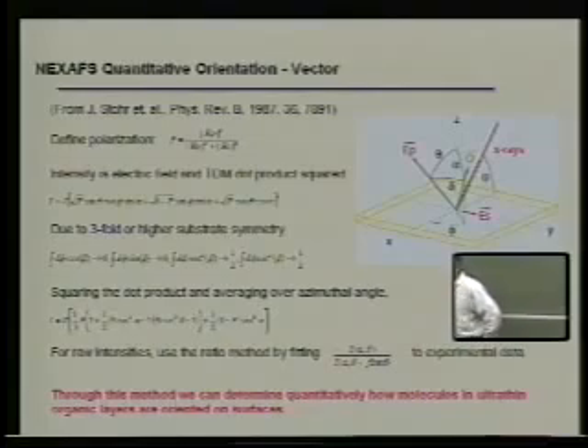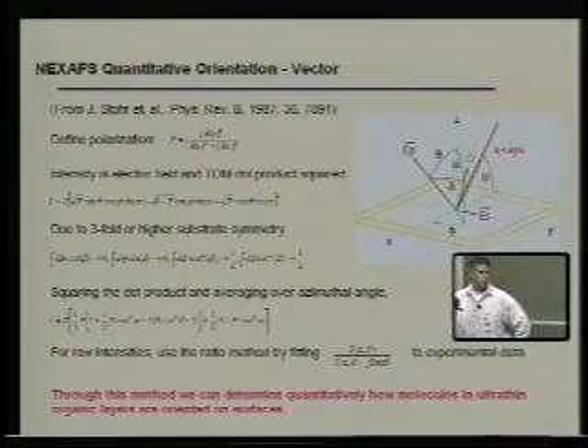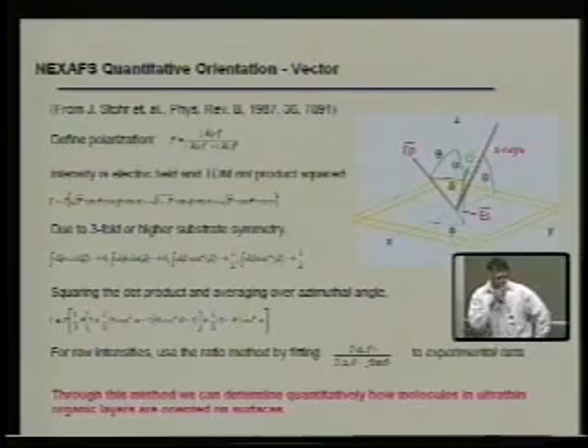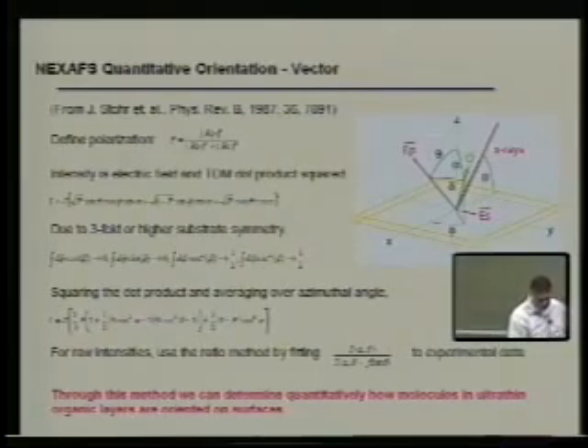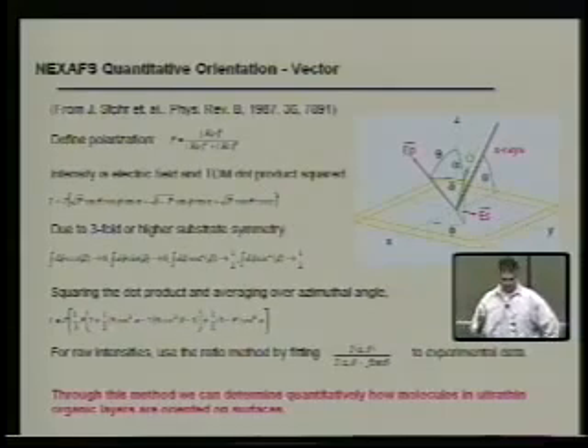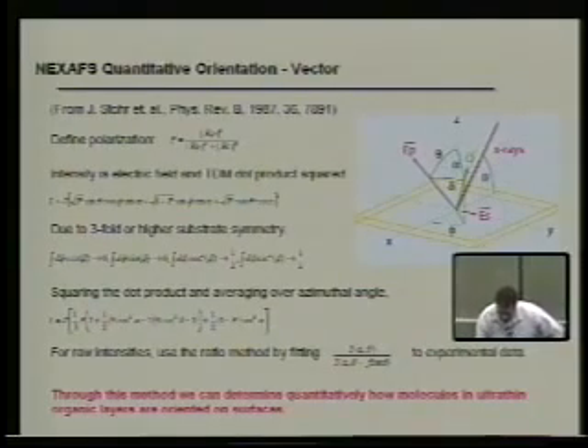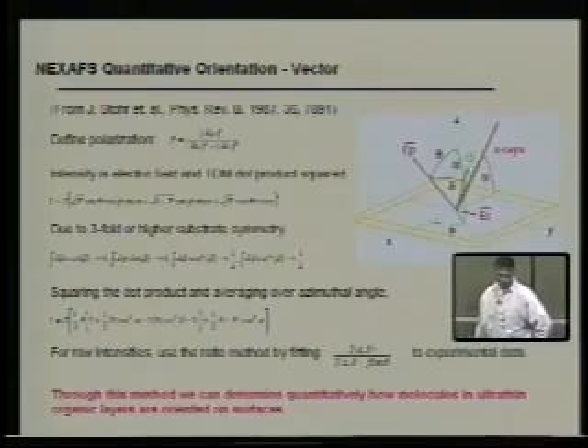So you have one intensity that you can measure in your X-ray absorption. You have three unknowns. But in this case, you have a threefold symmetry, and a number of these terms will actually drop out, and it gives you this dot product that's at the bottom. That's I versus alpha, theta, and phi.